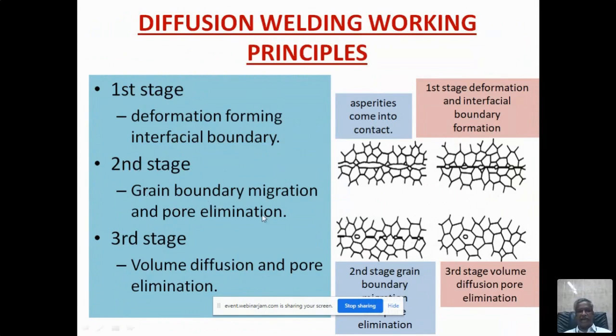In the second stage, the grain boundary migration will happen like this. The grain boundaries will move, and there is pore elimination. What are the pores? These are all the pores. Pores mean there's a gap between the top surface and the bottom surface. Because of the migration of the grain boundary, the pores will be closed slowly. In the third stage, once this is closed, atoms are free to move, and volume diffusion and pore elimination will occur in the third stage.